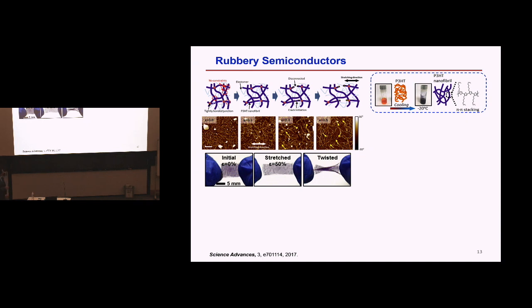We came up with a way to process the material using a cooling-induced assembly process to create this material. If you look at the microscopy of this material, the bright color represents the nanofiber structure, and you can see it is really percolated. This is at 10% mechanical stretch, and this is at 30 and 50%. We do observe some disconnection sites or breaking of the nanofiber structures, but overall, based on our device evaluation, these nanowire networks are still percolated and connected with each other, allowing the carrier to travel from one end to the other, which is very important for electronic transistors, right?